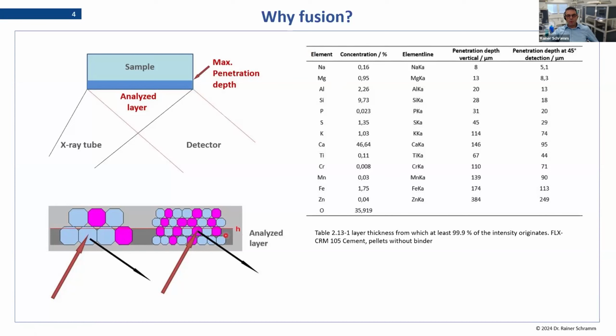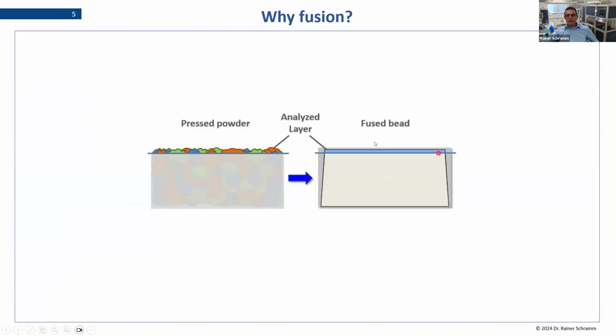And when we want to get it better, we have to dissolve the sample completely. If we look at a fuse bead, it is like a liquid, like tea where we put sugar in, and it's completely dissolved then. That's the same here in a fusion. That means our powder is completely dissolved into that glass, like into a liquid, so that we can assume we have a completely homogeneous distribution. And then if we analyze just the surface, this will be representative for the whole sample.